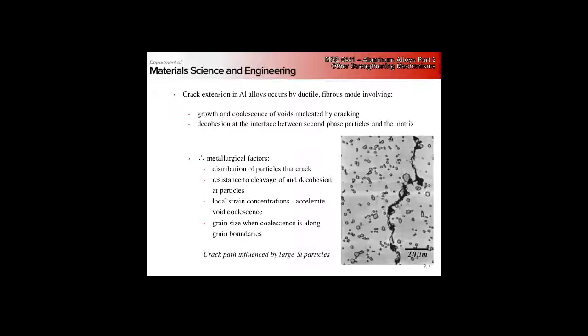Okay. So now if we have a series of large intermetallics, right, we can get, notice that the crack path follows the largest defects, largest particles in our structure here, right? So the distribution of particles is of prime importance, right? So if we tend to have large linear arrays of large brittle intermetallics, that would be bad, right? Right. What naturally happens when we roll our material? Right? We get just that, large linear arrays of brittle intermetallics.